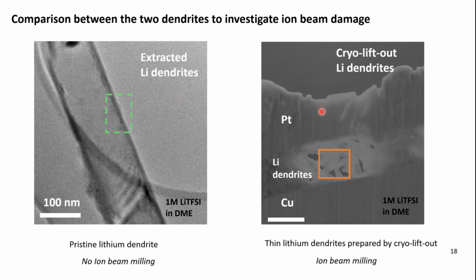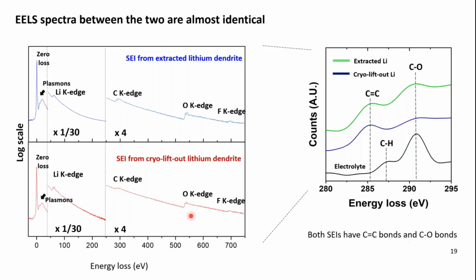And we also prepared another sample by the cryogenic lift-out technique. In order to match the same dendrite features, we used the same liquid electrolyte and concentration, and we used the same capacity and the same current density. I first looked at the bonding information using cryo-EELS, and the EELS spectra between the two turn out to be almost identical, meaning that the ion beam does not significantly damage the chemical bonds in the SEI. I zoomed in on one of the K-edges, which is the carbon K-edge in this case, and they form both C=C bonds and C-O bonds in the two different samples, one of which is extracted lithium and the other is cryogenic lift-out lithium.